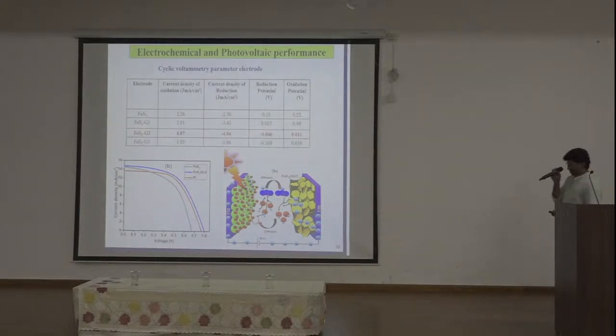And yeah, these are the cyclic voltammetric parameters. We can see the FeS2G2 sample has a high anodic current density as well as a high reduction current density. It indicates high electrocatalytic activity towards iodide and triiodide. And also the lower redox potential provides the driving force to reduce the electrolyte and improve the electrocatalytic activity.